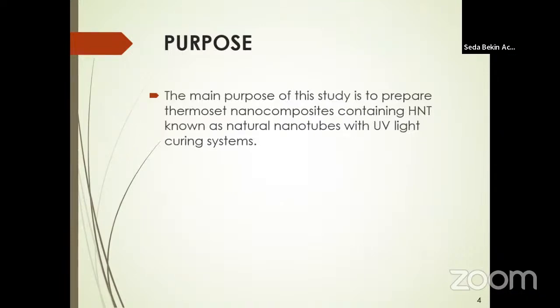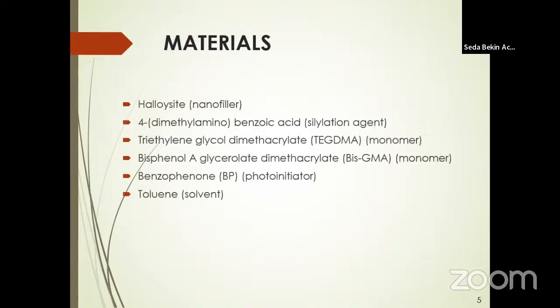The main purpose of this study is to prepare thermoset nanocomposites containing halloysite, known as natural nanotubes, with UV light curing systems. The chemical materials used in the study are as follows: halloysite as nanofiller, 4-dimethylaminobenzoic acid as silylation agent, triethylene glycol dimethacrylate as monomer, bisphenol A glycerolate dimethacrylate as monomer, benzophenone as photoinitiator, and toluene as solvent.